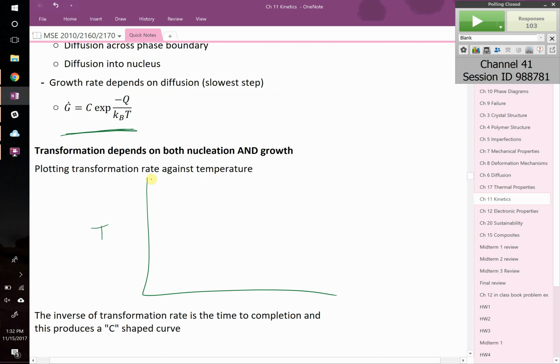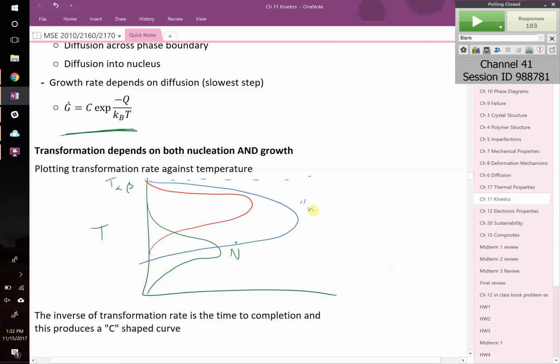Again, plotting as a function of temperature. You've got the temperature where you expect it to happen. They show that your nucleation rate is down here, and with a dot. And then they show growth as being something higher, where you get maximum growth up here. And so for your overall transformation rate, this is the one that matters, you get this N shape, this cone, they call it a nose-shaped curve, right? Because you're multiplying your growth by your nucleation rate, okay? And this is maybe intuitive. What this means is that as you're below your melting transition point, the point where you expected it to happen, there's some temperature right here where you get the fastest rate. That's your fastest rate of transformation.